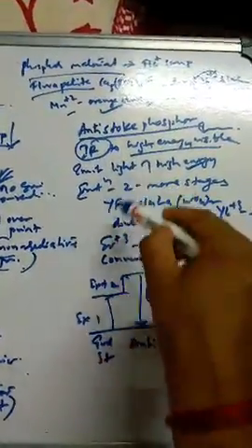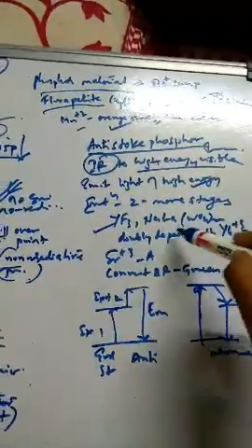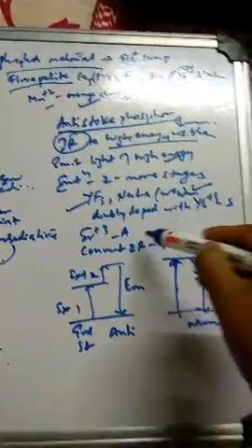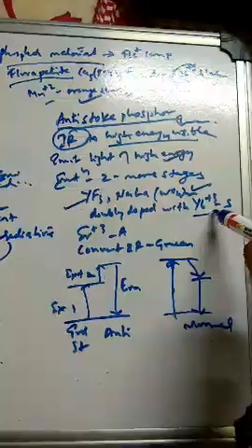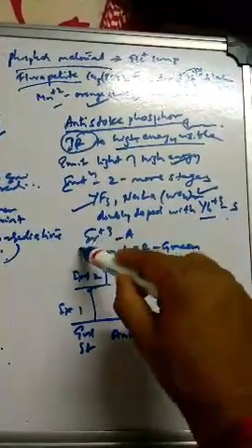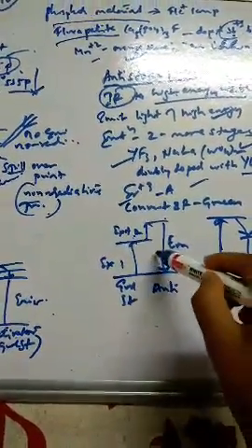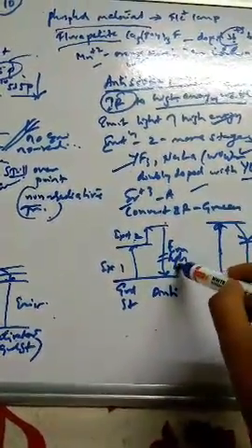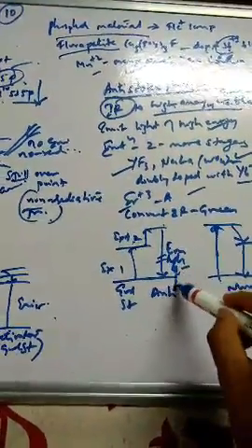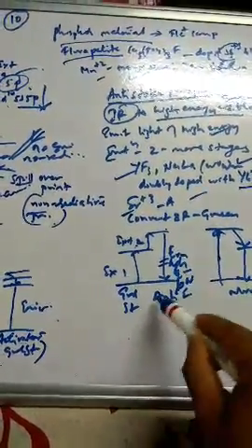The best examples for anti-Stokes are yttrium fluoride, then sodium lanthanum tungstate, NaLa(WO4)2, doped with Yb3+ as a sensitizer and erbium as an activator. So you can see here, this is the first excitation state, then the second excitation, then emission takes place. This emission will be of high energy, that means low wavelength. This is called anti-Stokes.